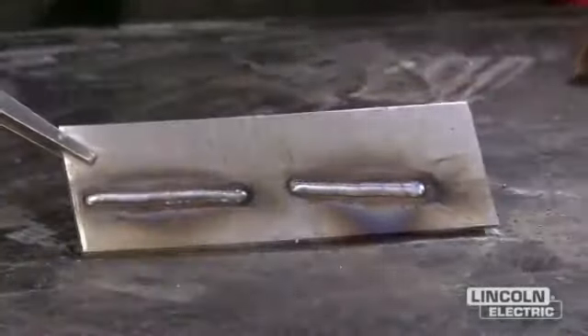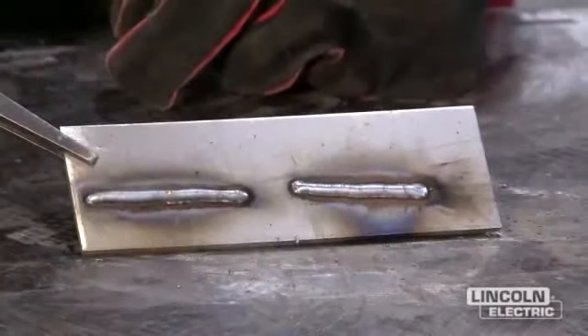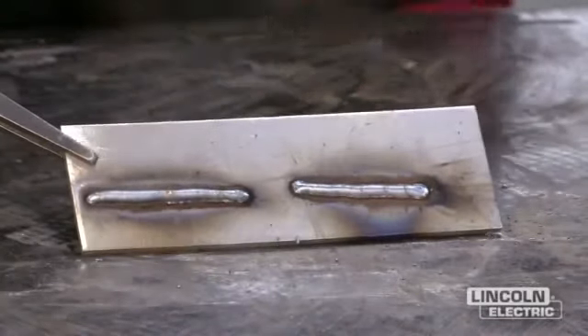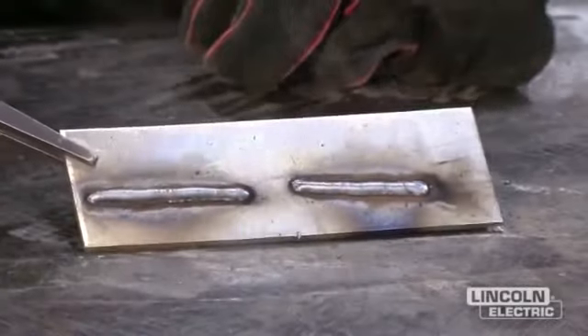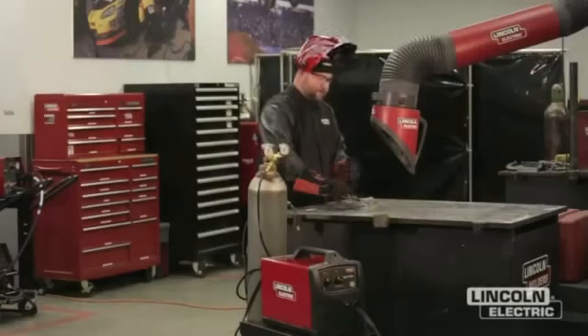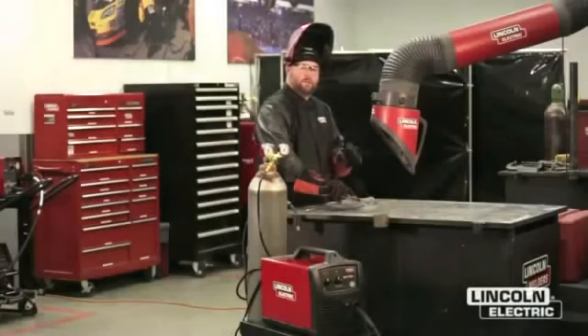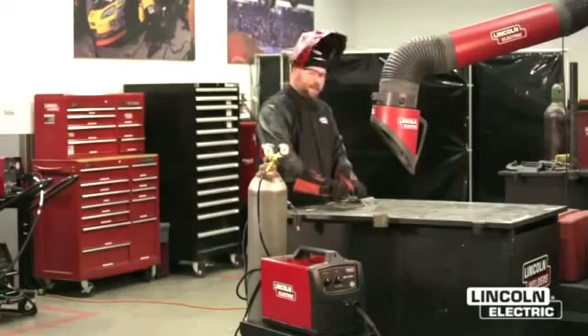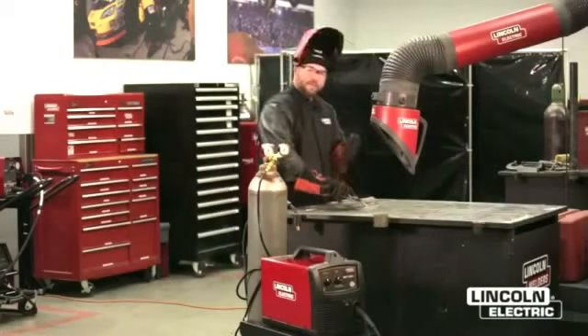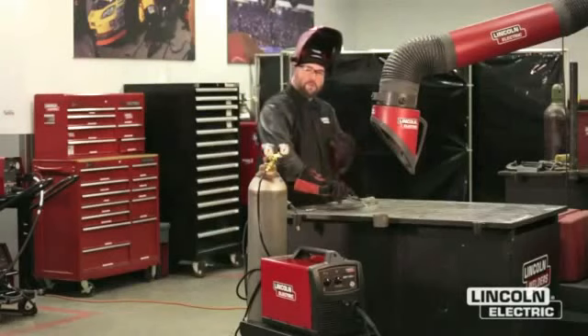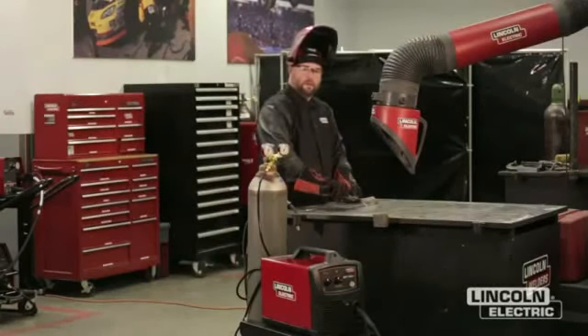So now if we look at the two welds we just made, the first one being too high a wire feed speed and the second one being too low a wire feed speed, we noticed on the second one that we made, we could see those droplets coming off there and they were very large. So we'd have to adjust for that. Again, we can either take our wire feed speed up or bring our voltage down to make up for that.